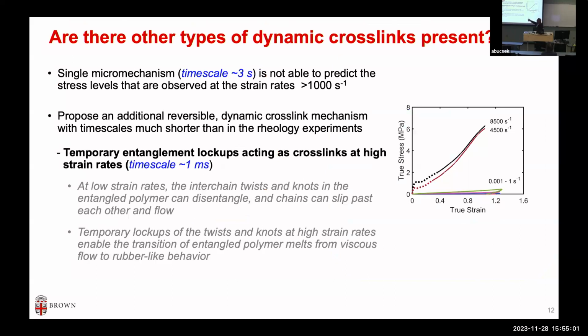So we found the time scale to be around 3 seconds, right? That's where you're looking at the fluid flow. Now the question is, is there any other cross-linking mechanism, some other physics going on that other people don't know about? What we found in our own experiment at the very high rate, by the way, I skipped over the details, doing the high rate experiment and getting a good stress-strain curve for the soft material by itself is very challenging. So we found collaborators who spent 4 or 5 months to get this data.